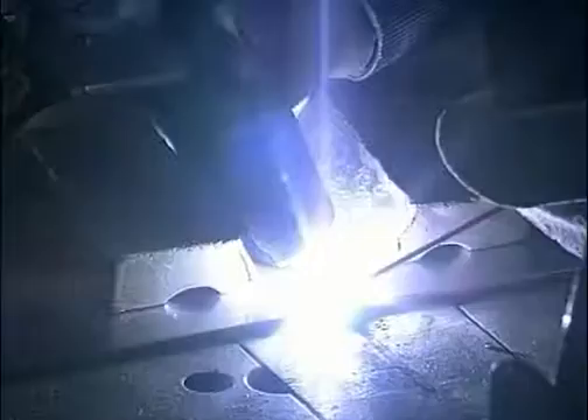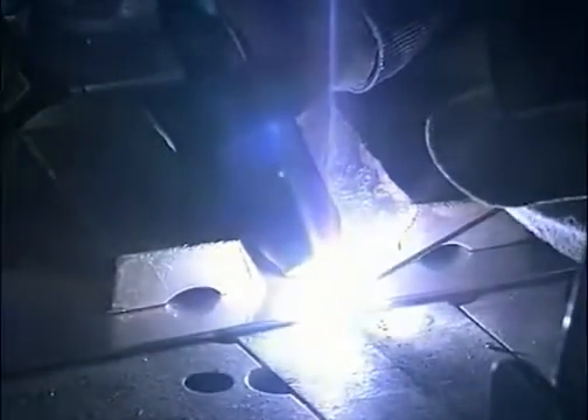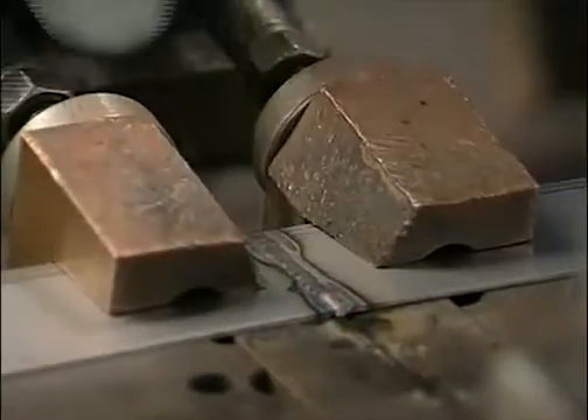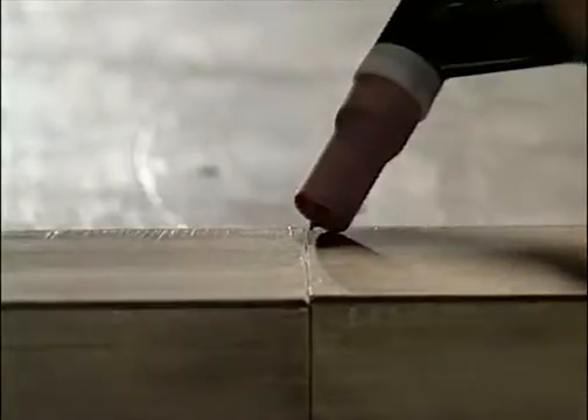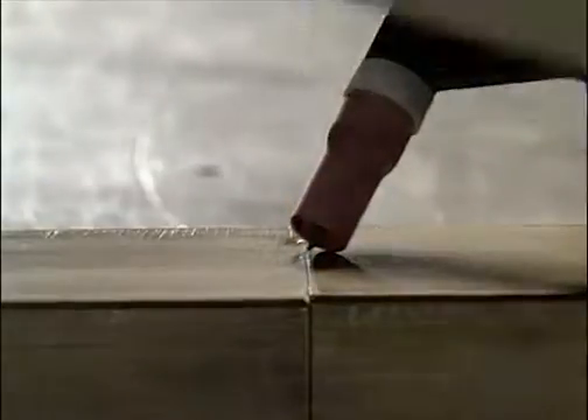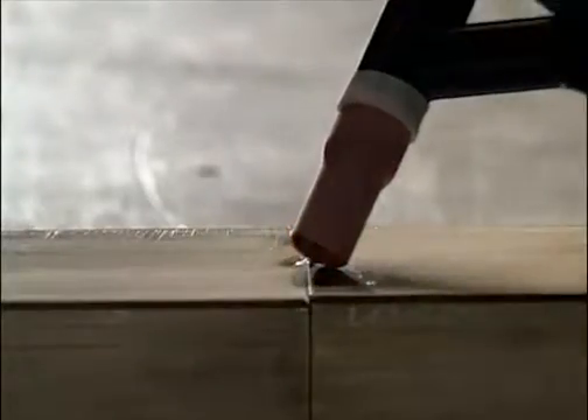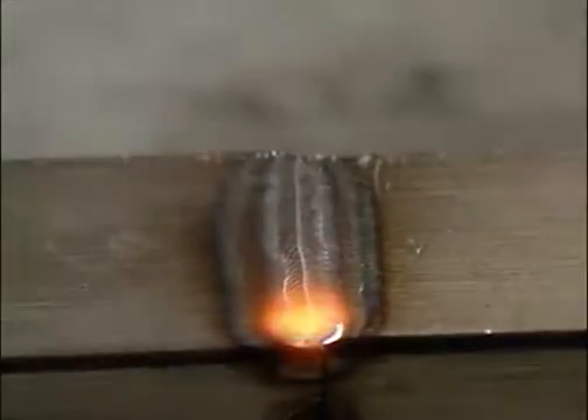This is TIG welding, and a filler wire is being used to add extra stainless steel to the weld pool. If it isn't possible to use a jig, then tack welds can be used to prevent movement during welding. The tacks should be close together and small enough to be absorbed in the final weld.